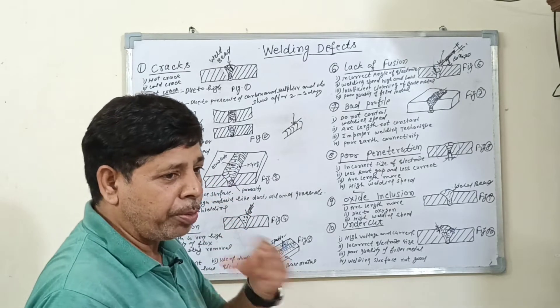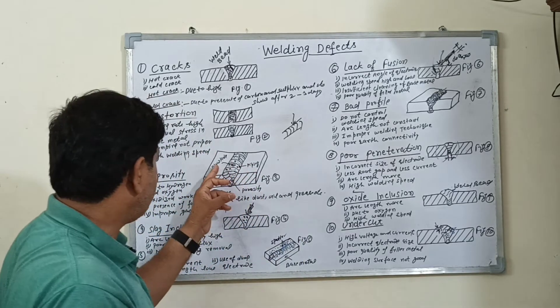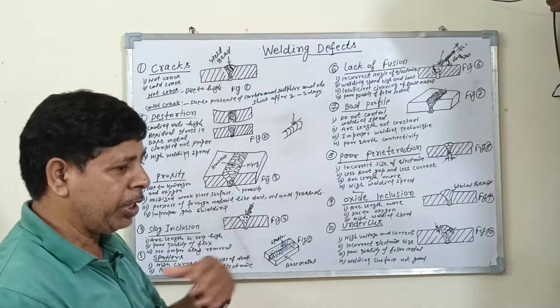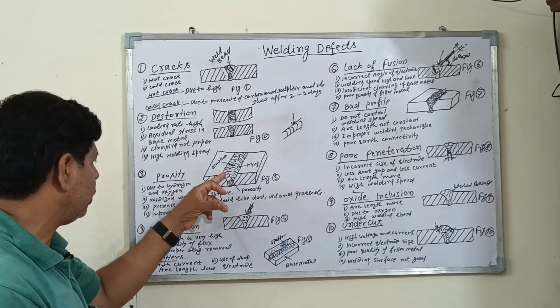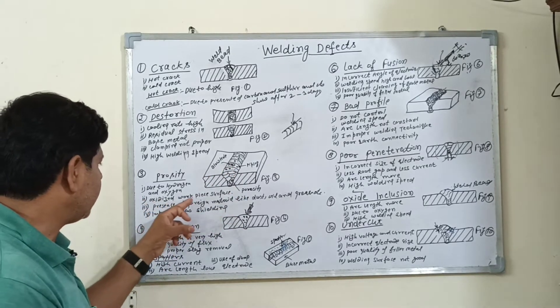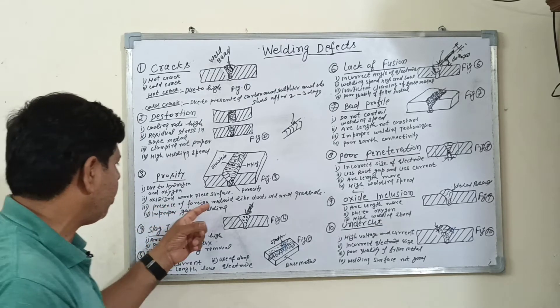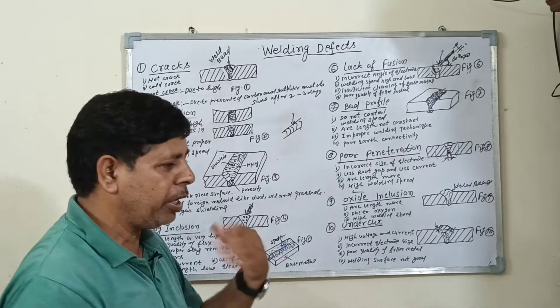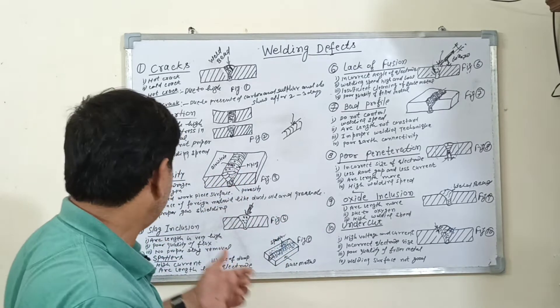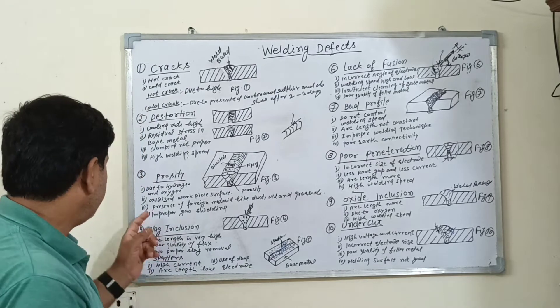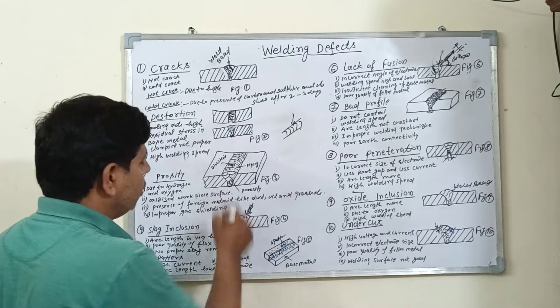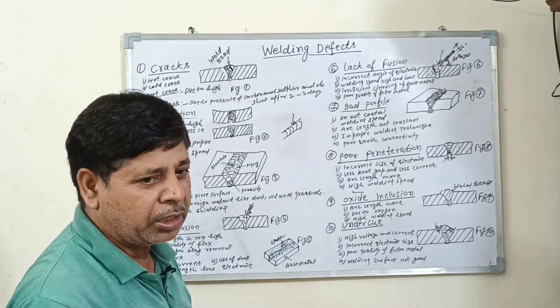Third number is porosity. Porosity means there is a group of voids in the metal, like blowholes, piping, and porosity. The reasons behind it include hydrogen and oxygen, which cause porosity and piping. Other causes are oxidizing the workpiece surface, presence of foreign material like dust, oil, and grease — the area should be neat and clean before starting the welding — and improper gas shielding. Proper gas shielding prevents oxygen and hydrogen from entering the welding zone.